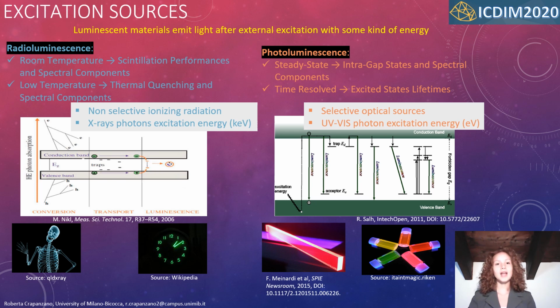The transport and luminescence steps of radioluminescence can be further investigated performing radioluminescence measurements as a function of the temperature. On the other hand, in photoluminescence, it is possible to selectively excite transitions between the delocalized bands or between intragap states. Hence, the decay time of a certain emission band can be studied.